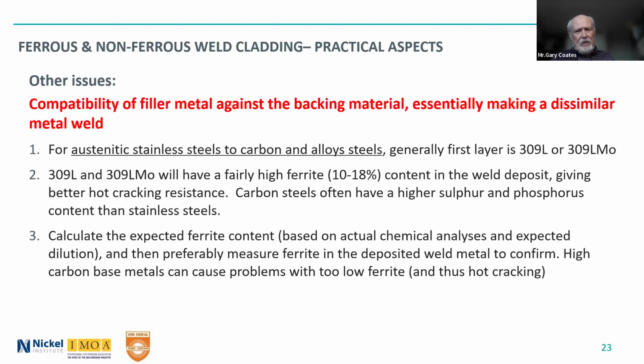And then you have to estimate the amount of dilution. What most people will do, let's say you're doing gas metal arc welding, which has a wide range, is say, okay, with the amperage that I specify in my WPS, it'll be 15% dilution, but you might want to look at both 10 and 20% dilution, sort of extremes there, to see whether you're covered just in case something happens where we're on the night shift when nobody is looking and the welder wants to get it done quickly. The high carbon base materials, for example the 1040 carbon steel with 0.4% carbon, even with the 309L, can result in too low ferrite and hot cracking.